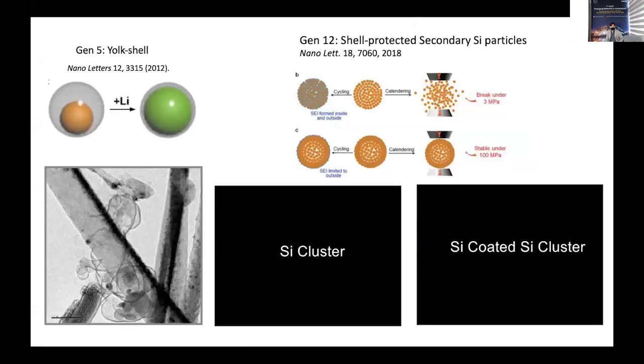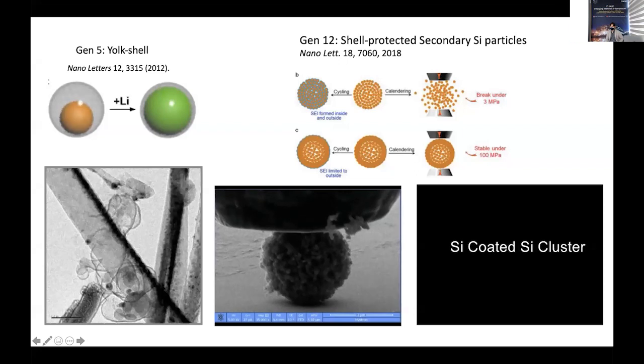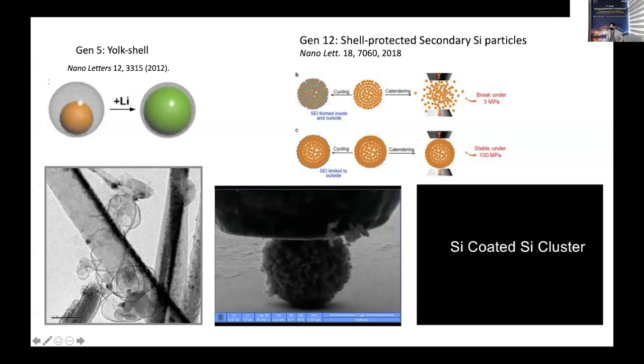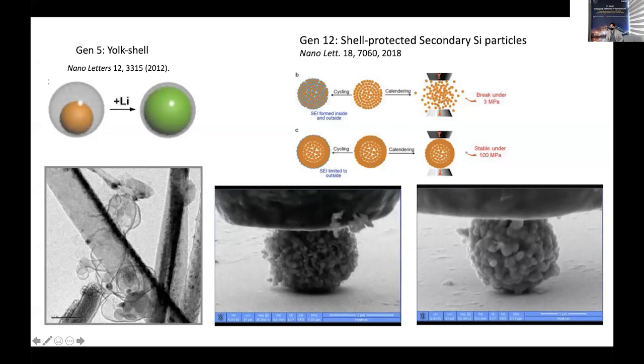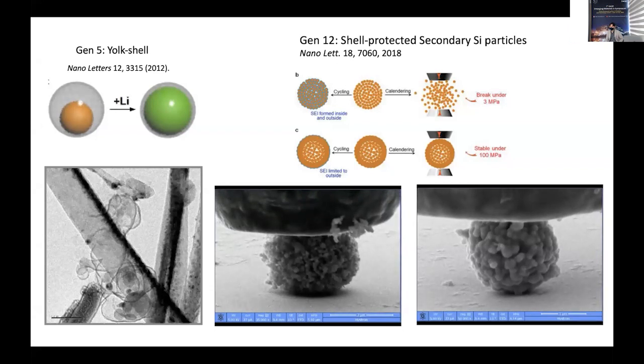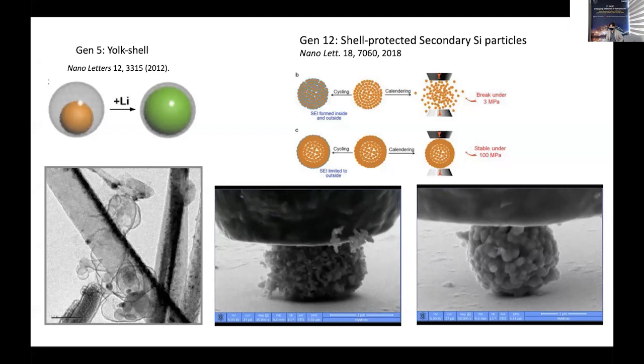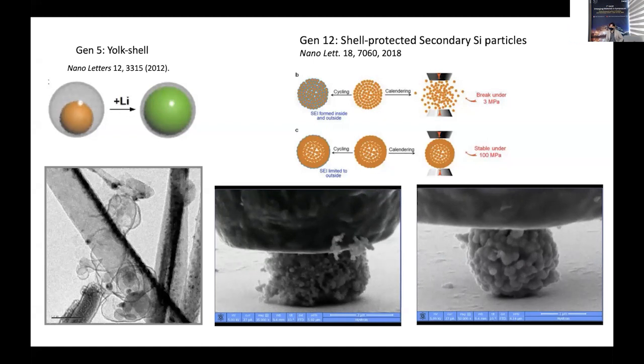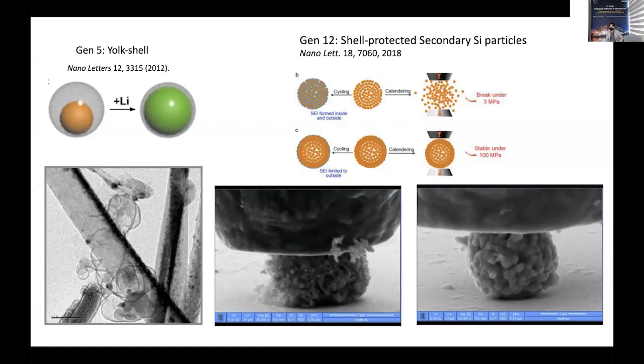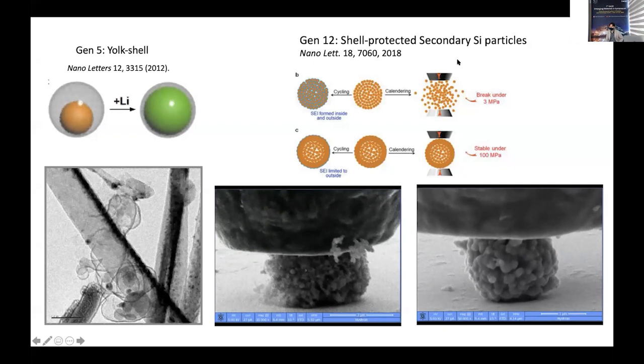Let me show you the video of the silicon cluster pressed under mechanical indentation. The left-hand side has no crust, as you can see, and this nano indenter inside the SEM will break this particle. But the right-hand side, with the silicon CVD shell right there, will keep the whole structure together to have only elastic deformation. So using this design, we can take on pressure as high as 100 megapascals, and that really allows us to stabilize this particle for calendaring to make the real improvement in battery performance.